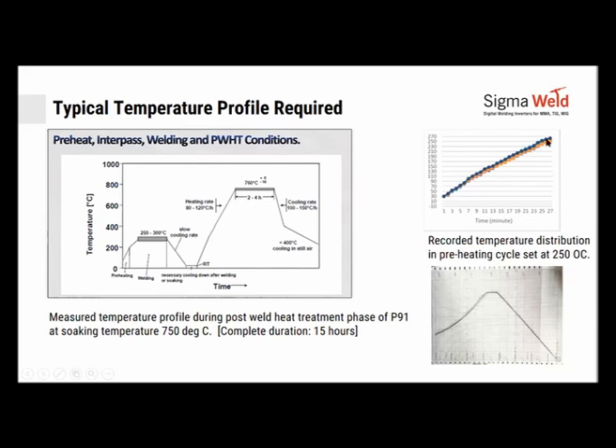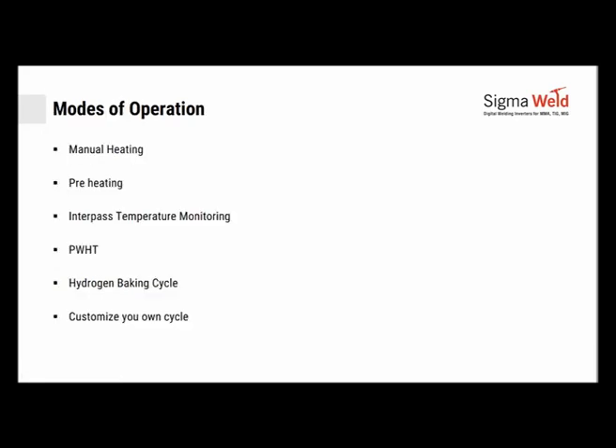On preheating, you can see that the thermocouple on the outside and on the inside, the difference is minimal, and the temperature range is achieved much faster. Similarly, look at this chart, which was produced during the post-heat cycle. The cycle was completed in 15 hours. You could have a gradual ramp up as you programmed, hold the temperature there for a couple of hours, and then a gradual cooling down, and then bring it to a nominal temperature and let it cool.